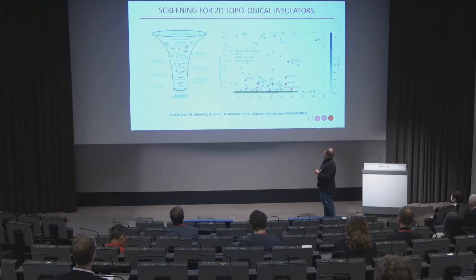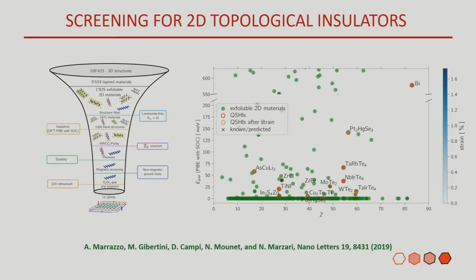5,619 layered materials, 1,825 exfoliable. We don't study materials containing lanthanides because it's still too complex to identify the magnetic structure and to be accurate in it, but on everything else, we do our quantum mechanical calculations. For those of you that are experts with spin-orbit coupling, we calculated the Chern invariants, and if a material looks promising, we do many-body perturbation theory to calculate correctly the band structure.